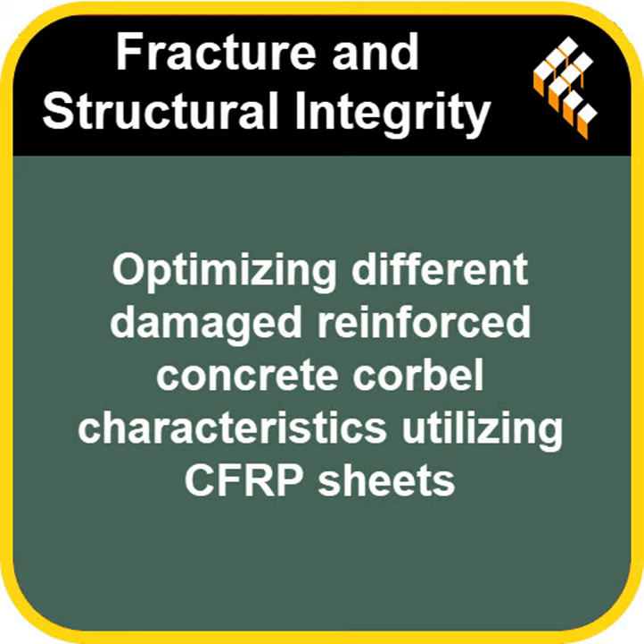And how did they use the CFRP? They tested two main strengthening configurations using CFRP sheets. Configuration 1 was full-side wrapping, covering almost the entire side face of the corbel. Okay, total coverage. And Configuration 2 was strip wrapping. Here, they applied CFRP strips only over the areas where cracks were expected or had already formed in the damaged specimen. More targeted. Exactly.